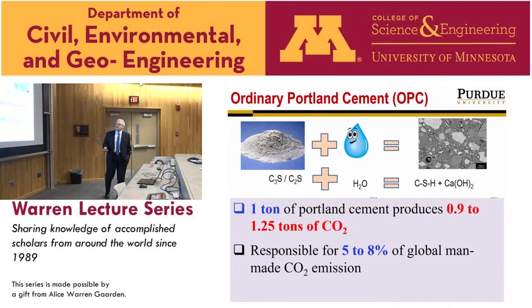But the issue is that when we add the balance of CO2 production, 1 ton of Portland cement results in about 0.9 to 1.2 tons of CO2, depending on what method and what type of cement we produce. There's variability, but if you remember, 1 ton of cement, 1 ton of CO2, and you look at 4 billion tons, that would produce a lot of CO2. So the cement industry is responsible for about 5 to 8% of global man-made CO2 emission. Cars make more CO2 than cement does, but the cement industry became a target of very concentrated efforts to reduce the CO2 associated with the production of clinker.